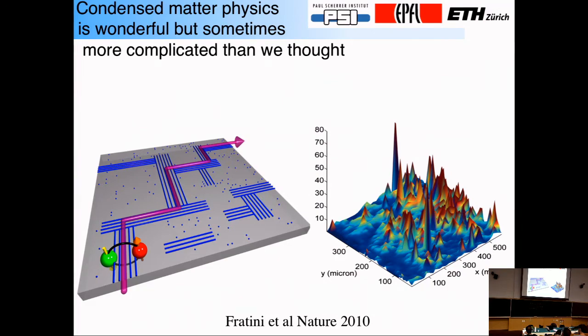In fact, the high temperature superconductors, at least some of them which have been optimized, are hardly homogeneous materials, and this just shows an X-ray scattering experiment which shows in what sense these materials are inhomogeneous. It doesn't matter. The fact is that this X-ray diffractogram is very position dependent, even though the material is a very nice superconductor and itself looks chemically homogeneous from the point of view of X-ray diffraction. It in fact is not.